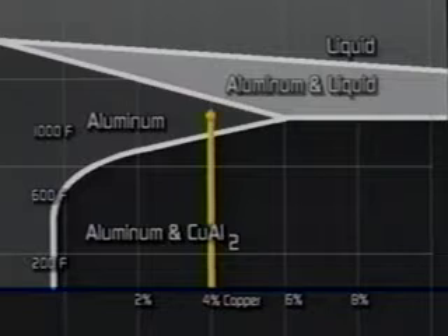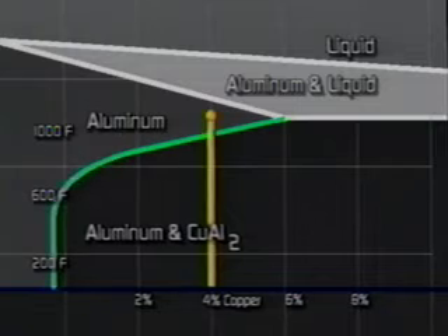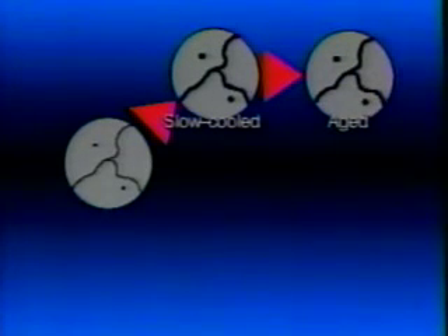In order to fabricate a useful shape from this material, we may forge the material, or extrude it, or roll it. And this mechanical working of the alloy requires a temperature at which all the copper is in solid solution. As the forging or the rolled plate cools slowly to room temperature, the ability of the aluminum lattice to hold the copper atoms in solid solution decreases. This means that more and more copper atoms leave the aluminum lattice and form particles of phases which are rich in copper. During slow cooling, these particles grow in size and become distinct from the aluminum lattice. As a result, the microstructure consists of an aluminum lattice containing a few copper atoms in solid solution and large particles of copper-rich phases. This structure is low in strength and low in toughness. In other words, it is useless as an engineering material.